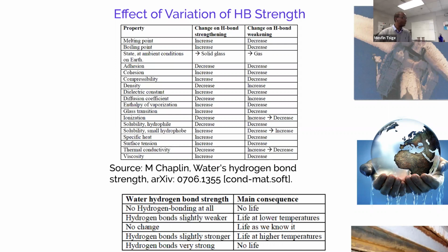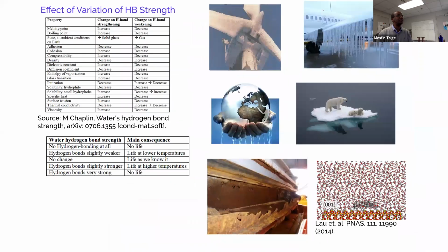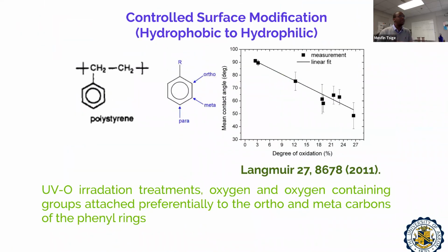In effect, what we know is, if there was no hydrogen bonding at all, if we had a mechanism of turning off the hydrogen bonding, the boiling point of water would be around -80 degrees centigrade, which means life wouldn't exist without hydrogen bonds. Hydrogen bonding is key for us to live on this earth. If we make it weaker, of course, life would have been at a lower temperature. No change means life exists as we know it. If we make it stronger, then we could pretty much go to higher temperatures. So we connect all the properties of water with this hydrogen bonding. So in my case, I was really motivated by this experimental work that was published in 2011.